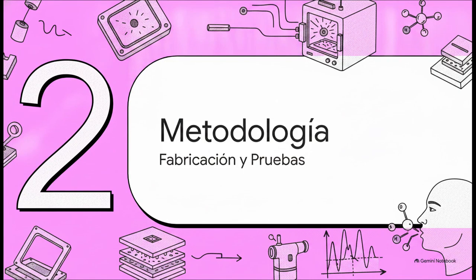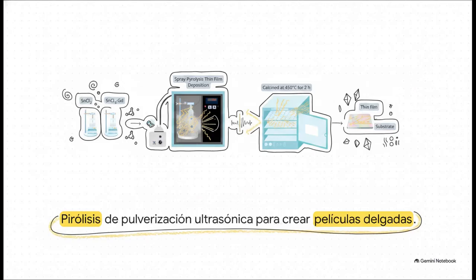Moving to Section 2, let's talk about our methodology for sensor fabrication and testing. To build these films, we went with an ultrasonic spray pyrolysis system, or USP. Now, if you've worked with USP, you know it's a real game changer for straightforward, cost-effective, and highly controllable thin film fabrication. We deposited our pure and gadolinium-doped tin dioxide films over 3 distinct time windows: 90, 110, and 130 minutes. Once that deposition was done, we calcined the samples at 450 degrees Celsius for 2 hours just to really lock in and consolidate that structure.